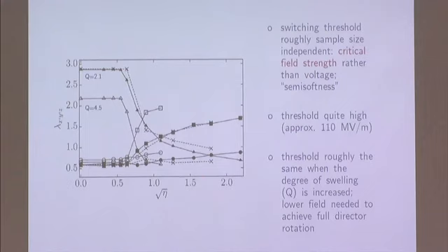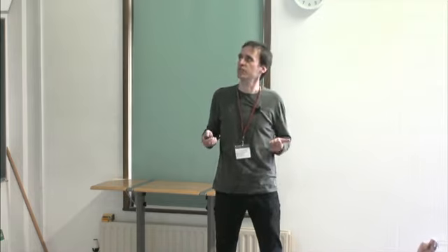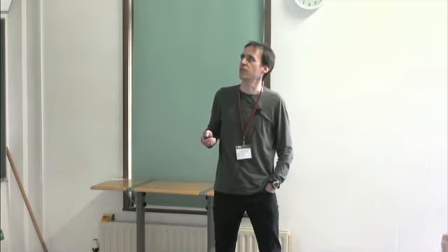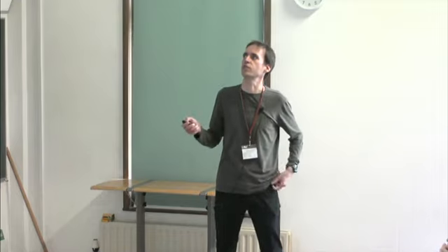This is as opposed to a similar phenomenon seen in monomeric liquid crystals, the so-called Frederiks effect, where you have walls, a surface anchoring, a surface effect that contrasts the applied bulk field. In the Frederiks case, you end up with a so-called critical voltage. However, since we have a bulk effect against a bulk effect, we end up with a critical field strength.